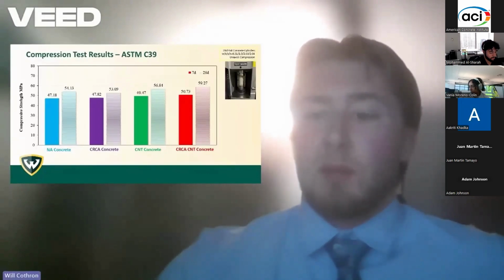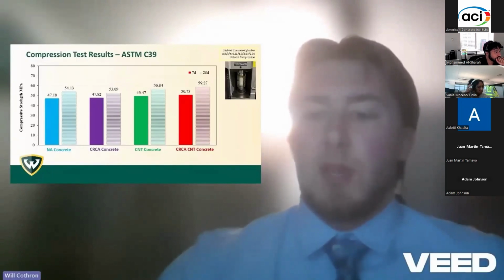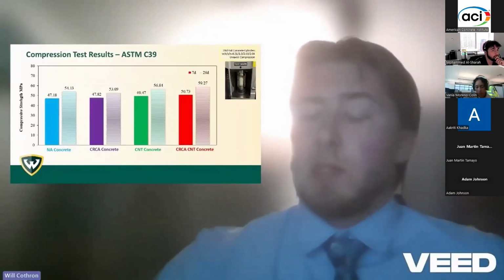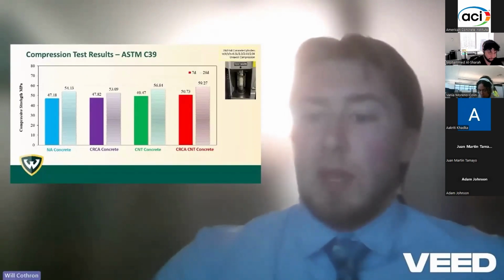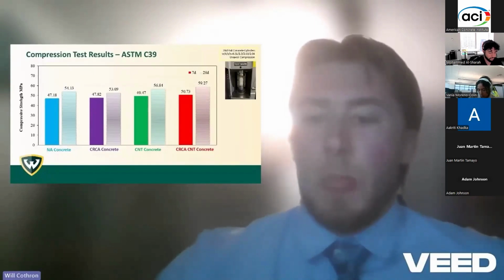Typically, using recycled concrete aggregates in concrete mixes can reduce their strength due to the presence of weaker old mortar layers. However, our results indicate that carbonation significantly enhances the properties of RCA. Carbonated recycled concrete aggregate concrete exhibits similar strength to the natural aggregate mix, reaching around 48 MPa at 7 days and 53 MPa at 28 days, indicating the carbonation effectively overcame the typical strength reduction associated with recycled aggregates.